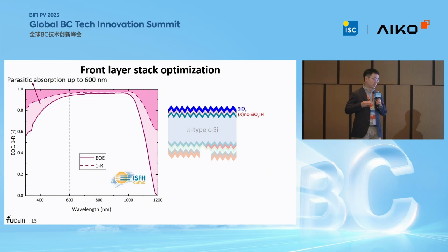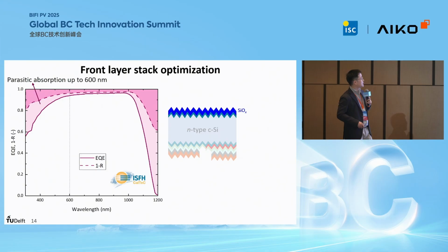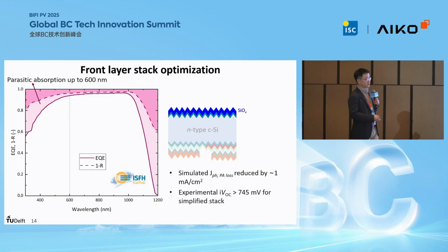And front-side optical management is important because we have to ensure that it's transparent while featuring minimized reflectivity without compromising the passivation quality. So firstly, we address the parasitic absorption loss. In this case, we removed the front surface field layer, the N-type nanosilicon oxide layers, and also we tried to minimize the intrinsic layers on the front side. According to our simulation, this could lead to a parasitic loss reduction of around 1 milliamp per square centimeter. And experimentally, with such a simplified front side structure, we also demonstrate implied VOC above 745 millivolts.